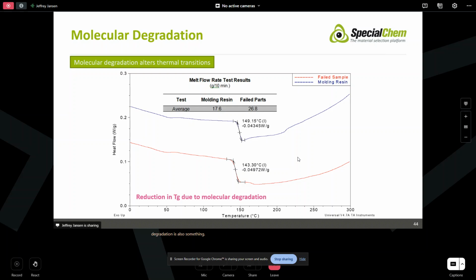Degradation is also something we can get a clue about with DSC. So here we had some failed parts, and we also had some molding resin. This is polycarbonate. The polycarbonate pellets give us a glass transition of about 149, right where we expect for polycarbonate. Our failed samples were down about 143. That 6-degree reduction is pretty significant, and it suggests that something is changing about the material.